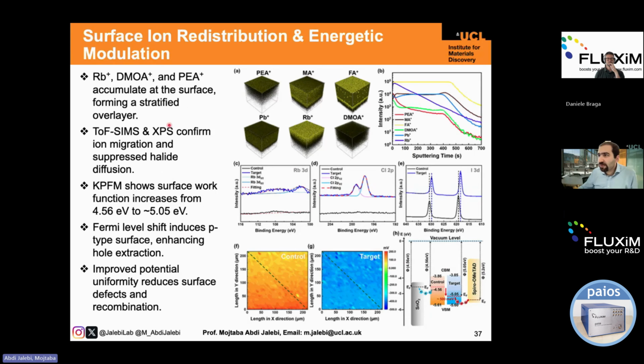So now let's talk about the distribution of these elements, as well as the passivation material that we have added to the system. In terms of the cation parts, it's mostly rubidium plus, DMOA plus, and PEA plus. You can see this is the Fluxim measurement we have done. It's the 3D topologies you can see, as well as the distribution from the surface. And obviously for the formamidinium, lead and methylammonium, the distribution is almost even, or homogeneous, within the perovskite structure.